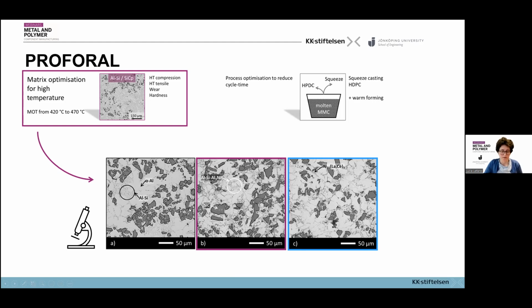The dark polygonal particles are instead our carbides, the reinforcement that is added to the matrix to build the composite itself. And then we can have additional intermetallic phases when adding alloying elements, as we said. For example, we can have intermetallics formed with nickel, still in the interdendritic space, or with lanthanum and cerium combined together. And all these phases contribute in a different way to the strengthening of the material.